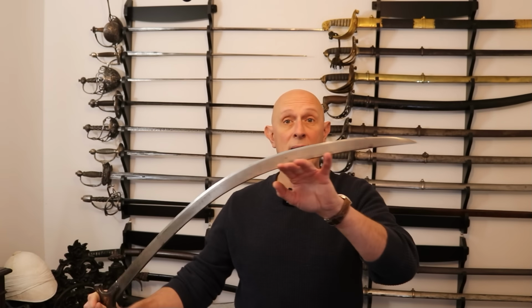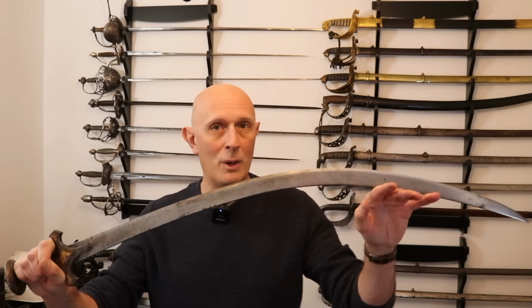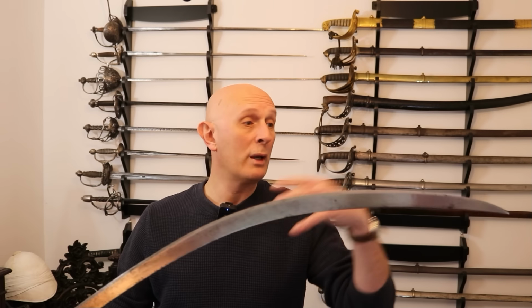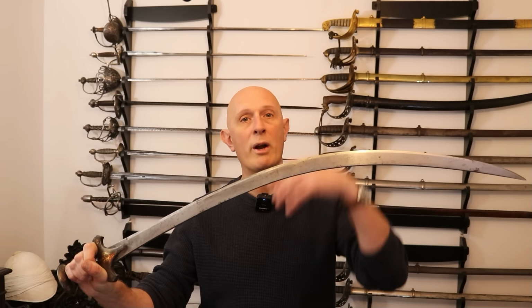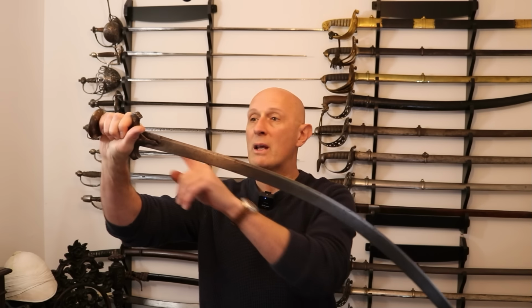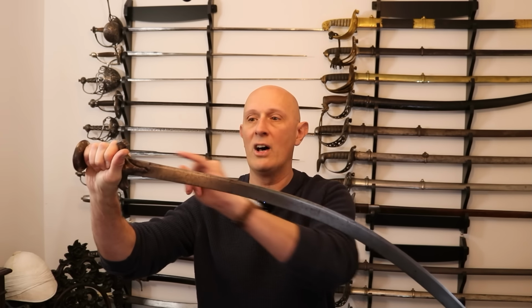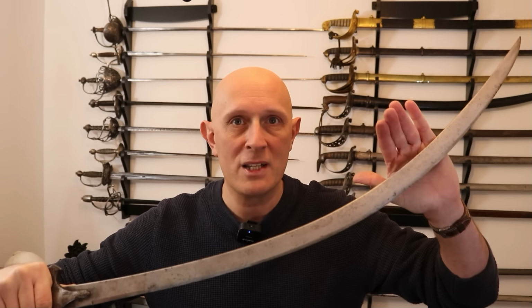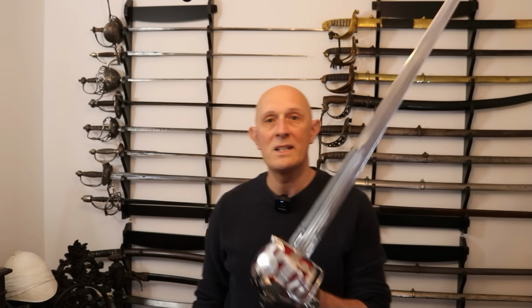And as we've said with Wootz blades, this is usually the case, and indeed it's usually the case with the traditional Indian tulwar. So in India, for example, we can find both types. We can find spring-tempered blades, which are through-quenched and then tempered, and then we can find probably the older type, which are only edge-hardened and left soft along the back, exactly like Japanese swords. So the question is, why did some people spring temper swords and others only edge harden them?